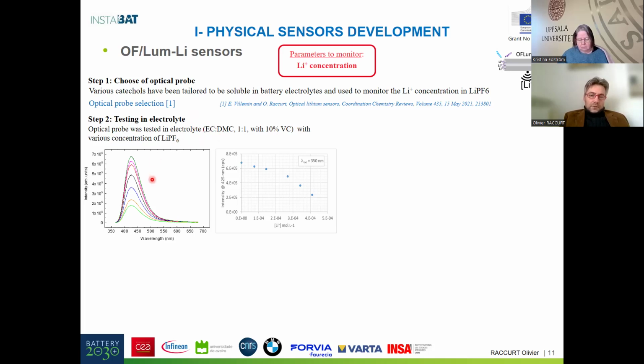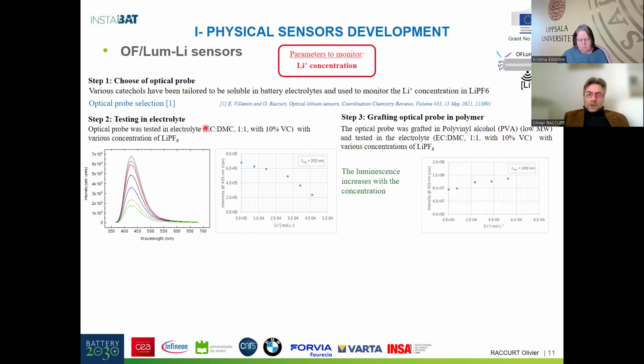And you can see here a result where we have the variation of the signal from the optical probe depending on the concentration of lithium. And if we plot the variation of the intensity as a function of the concentration of lithium in the electrolyte, there is a good variation of the signal, and we can in this way measure the concentration of the lithium in the electrolyte. But this probe is only a molecule. We need to attach this molecule to the fiber. For that, we need to attach this molecule into a polymer. We use the PVA polymer.